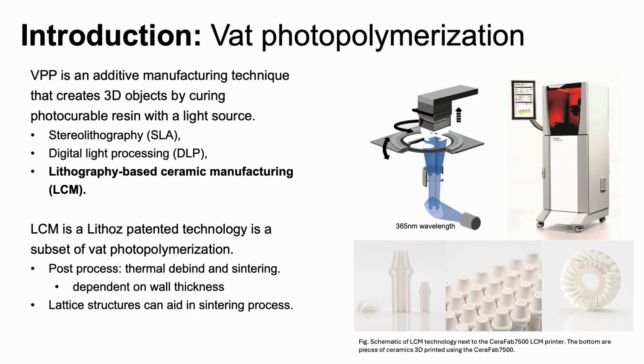So vat photopolymerization is the 3D printing technique that I use for this work. VPP for short is an additive manufacturing method that requires a photosensitive slurry so that a light source can cure the slurry layer by layer within the vat. There are multiple subsets of this technology, but we decided to use LCM, which is lithography-based ceramic manufacturing.